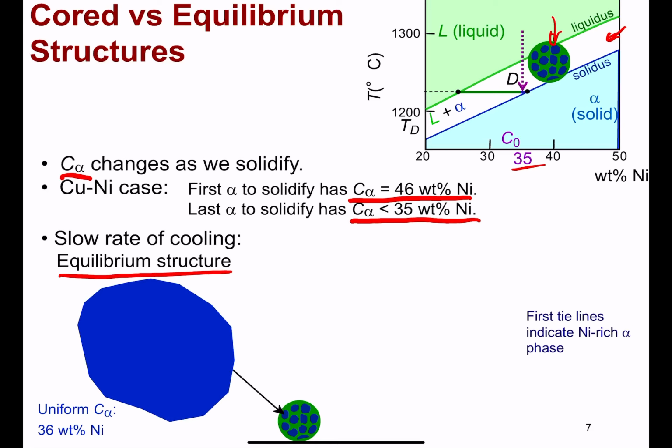Okay, so if we were to inspect one of these tiny little alpha particles and map by, say, a color shade for all the content that is 36 weight percent nickel at the point of around D, we would see that the whole alpha particle in this little red area is all uniform in its nickel content as estimated by the tie line approach of 36 weight percent.